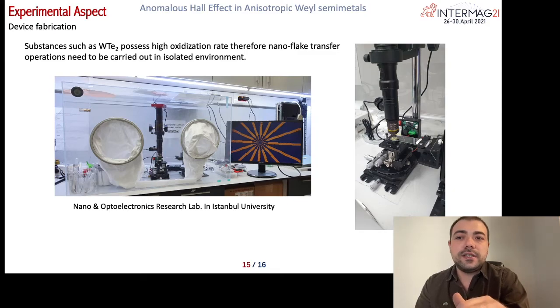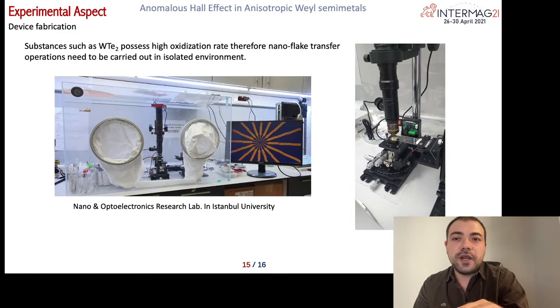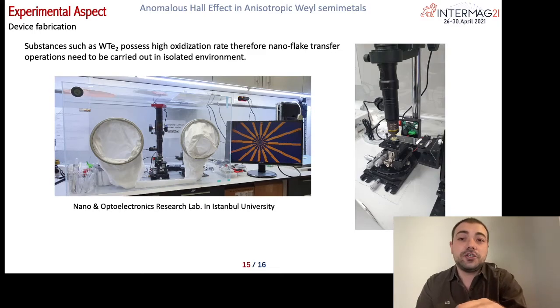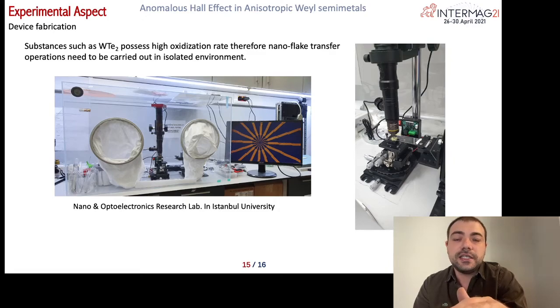Okay, the another point is that the tungsten ditelluride oxidization rate is not too low. Therefore, conducting the transfer and preparation operations of the nano flakes in the isolated environment is crucial to be able to measure clean signal in such difficult measurements like anomalous Hall.